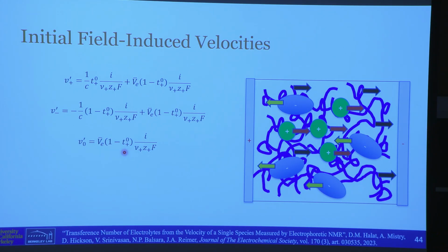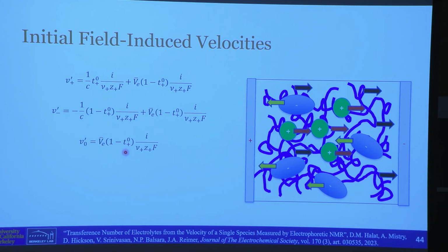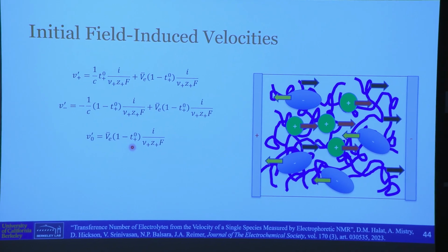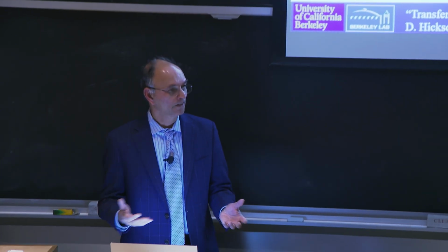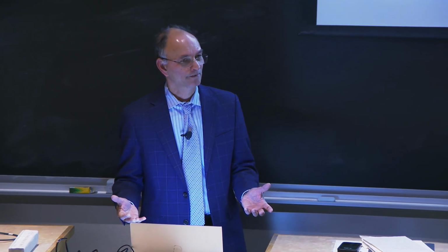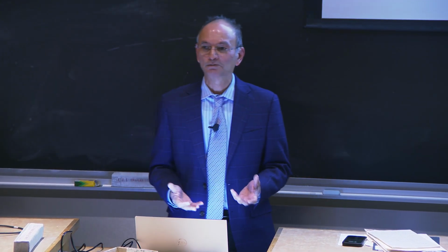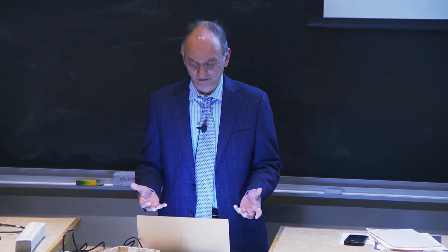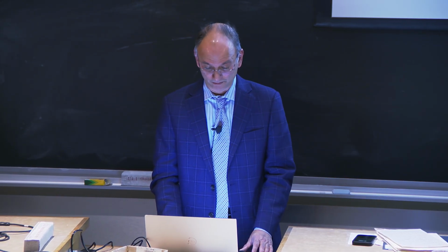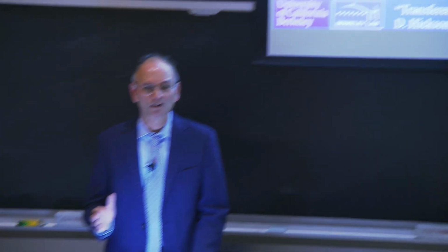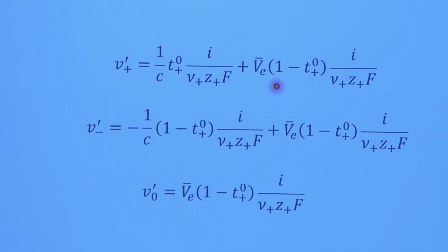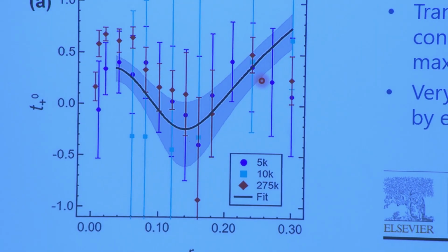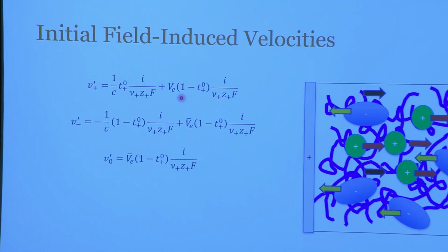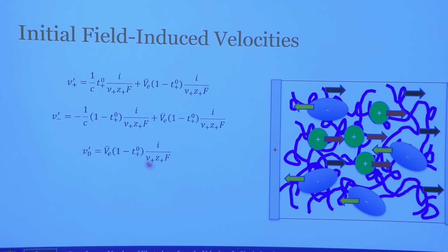The cation and anion are not symmetric at all in many respects. And when they start moving, whatever is left has to be taken up by the solvent. It's not negligible at all when any anion moves. And the extent to which it was negligible or not was never actually measured or predicted. VE, by the way, is the partial molar volume of the salt, which is never 0. So I want to come back and tell you about our tribulations of measuring this transference